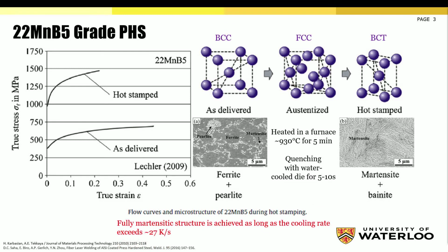During hot stamping, the material is heated in a furnace to about 930 degrees Celsius for about 5 minutes, followed by rapid quenching of the steel with a water-cooled die for about 5 to 10 seconds. The typical morphology of the material in the hot stamped condition is that of lath martensite.